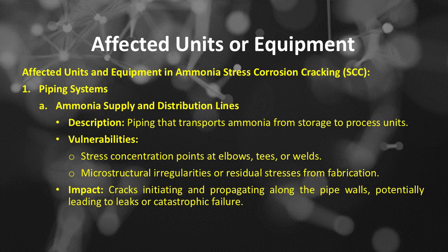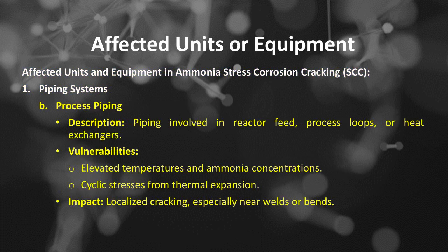and distribution lines, the piping that transports ammonia from storage to process units. The vulnerabilities of these ammonia distribution lines include stress concentration points at elbows, tees, or welds, and microstructural irregularities or residual stresses from fabrication. The impact would be cracks initiating and propagating along the pipe walls, potentially leading to leaks or catastrophic failure.